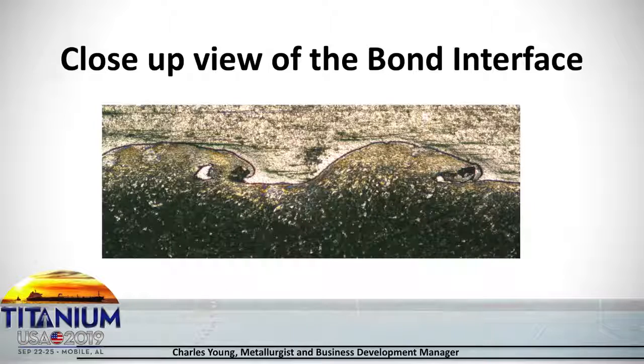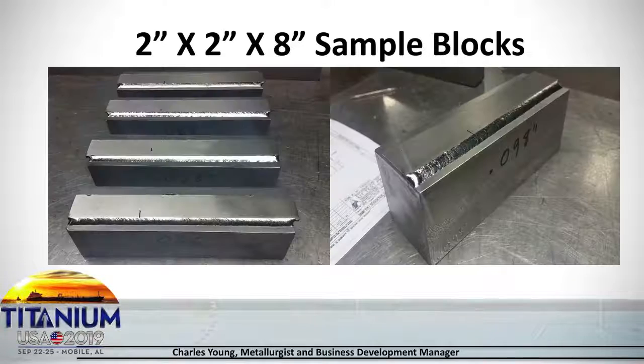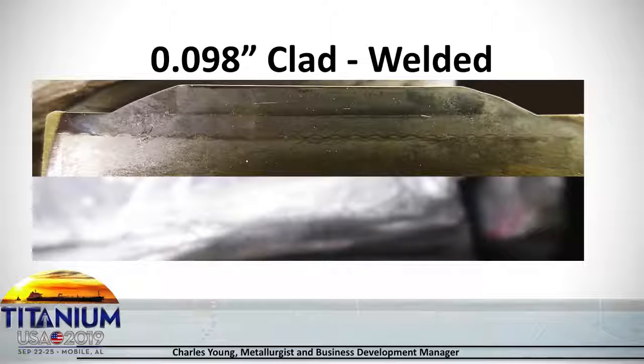These are just some pictures of the sample blocks with the actual welds. The 0.098" clad welded piece, you can see that, which one is the, whoop, I just turned it off. Here we go. Is this it? Yeah. You can see that there's no issues at the weld zone here, that the weld is very good, titanium to titanium. This is the steel backer. So there's no heat really getting into the steel here, so you're not getting any diffusion of steel or titanium into each other. So at 0.098", you're good.